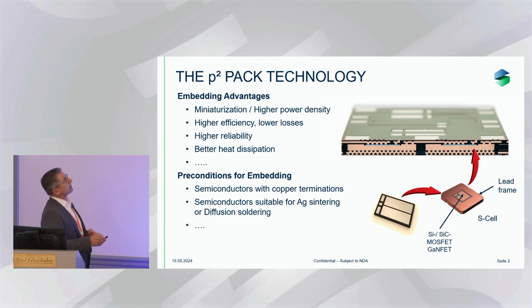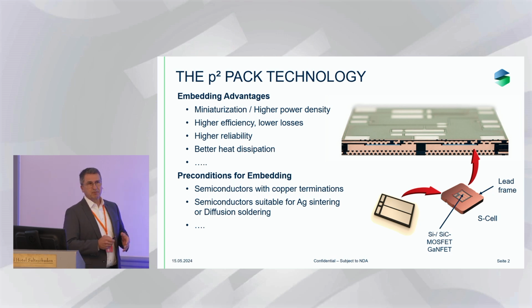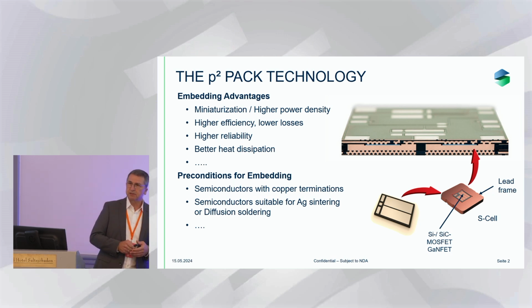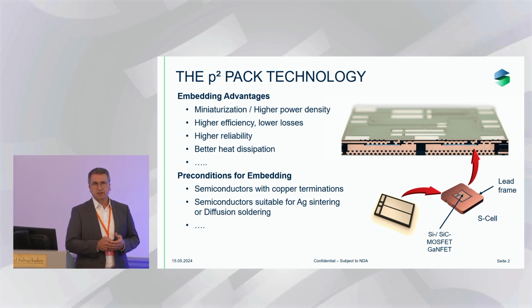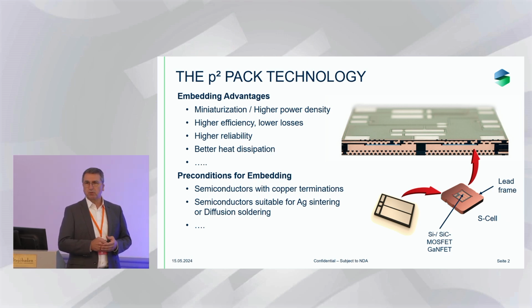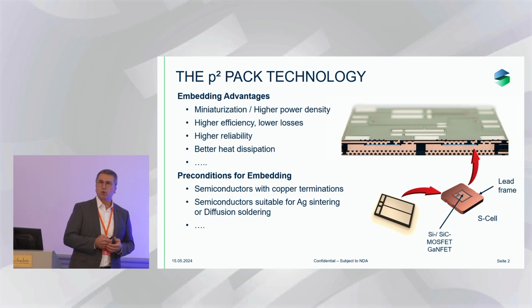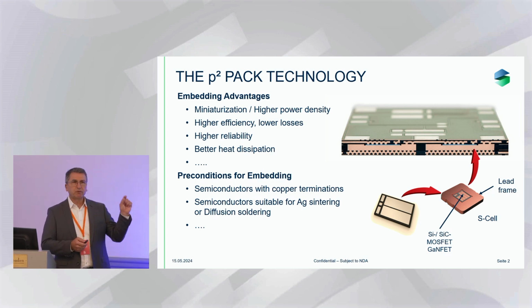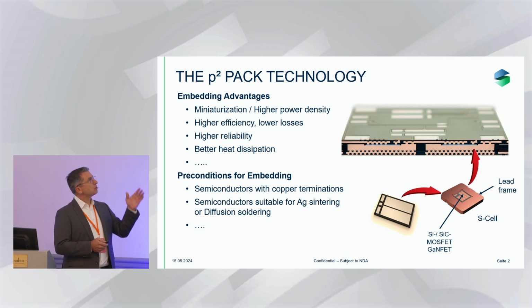And, kind of a surprise: if you're inside a PCB, you would expect that it's a problem to get the heat out, but we found that we can even surpass the thermal conductivity of power modules. The latest results from one of our customers was a module thermal resistance of 0.1 kelvins per watt with 4 components in parallel. So for the individual cell, you have approximately 0.4 kelvins per watt, even though it's insulated. And it's lower if it's not insulated.